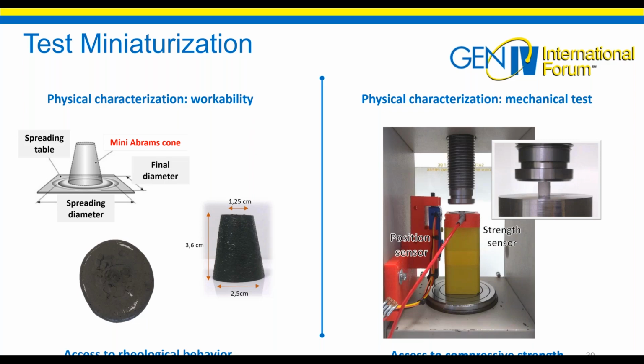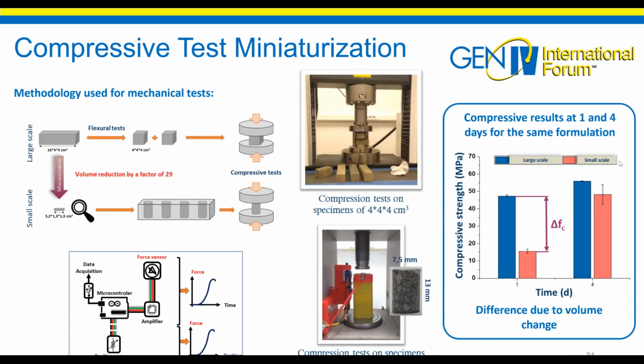Afterwards, the samples are mechanically tested. The characterization of the mechanical performance required the implementation of a small-scale setup. The tests carried out in the civil engineering laboratory are done on prismatic samples of 16 centimeters by 4 by 4 centimeters. After flexural tests, this gives 2 cubic samples for compression. Laboratory tests are performed on samples with a volume 29 times smaller, which allows me to have 4 cylindrical samples of 7.5 millimeters in diameter by 13 millimeters of height.